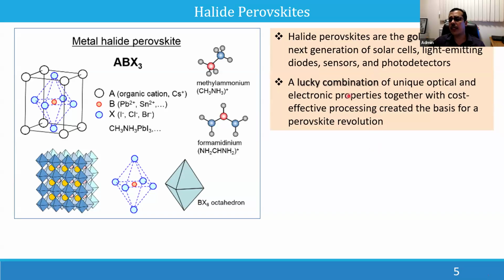Because here there is a lucky combination of unique optical and electronic properties together with cost-effective processing. The optical and electronic properties are coming from the inorganic clusters. These octahedral clusters are inorganic structures, and inorganic structures normally give very high optical and electronic properties compared to organic compounds. But at the same time, organic compounds have easy, facile processability and flexibility. Inorganic materials, on the other hand, are brittle and not flexible. They are hard materials, and their processability is very poor. So this is a lucky combination. The optical and electronic properties are governed by the inorganic clusters, while the processability is governed by the organic components.